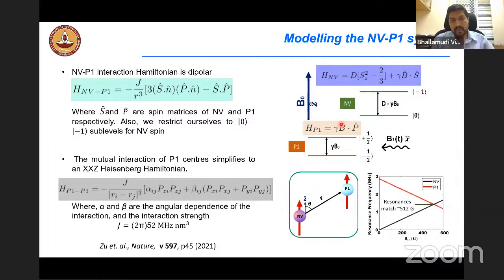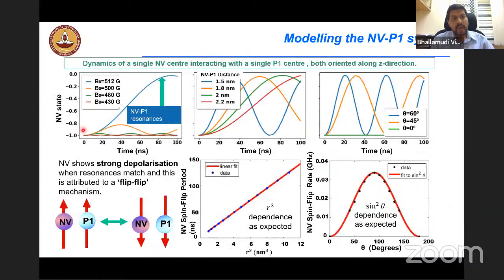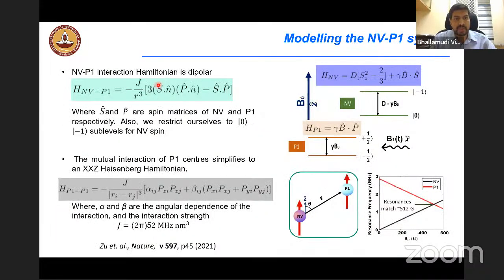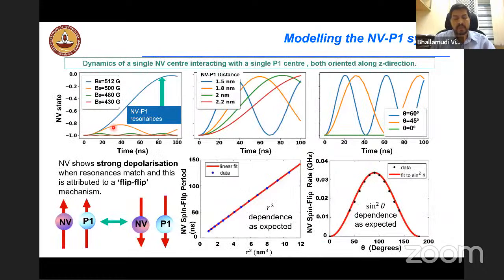And when we do all of this, we can understand how the NV and the P1 behave, first, in the simpler case where the NV and the P1 are resonant to each other, which is easier to understand. And so we have been able to verify that our model works. In this particular case, I think he is restricting his simulations to be between the NV and the -1 levels of the P1, where the NV levels are restricted to 0 and -1 sublevels. That's what he's looking at.